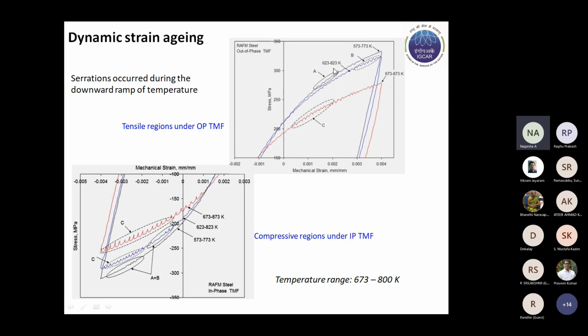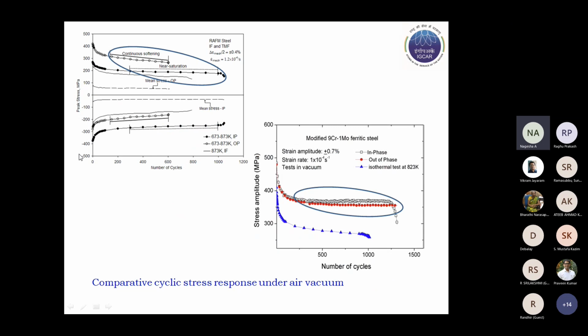In fact, lower temperature serrations are generally of A type, with intermediate temperatures they convert into B, and then in the higher temperature regime we normally see the C type of serrations. All this is happening during the cyclic loading. Depending on the temperature traversed, the type of serrations keeps changing from A to B to C. Similarly, in the compressive parts of the stress-strain loop under IP TMF, similar kinds of serrations were seen. So the occurrence of all these three mechanisms contributes to reduced cyclic life under OP TMF.